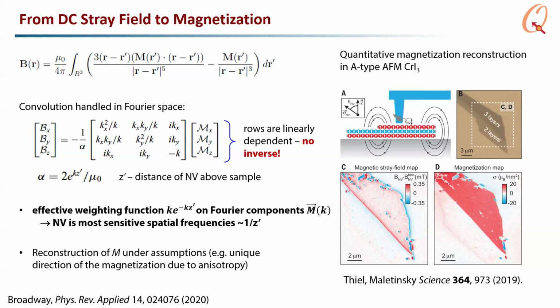Okay, so you'll also note that there's an effective weighting function, this k e to the minus k z prime, that modifies the magnetic field. So it really means that the NV center is most sensitive to spatial frequencies of order 1 over z, where z is the distance from the sample.